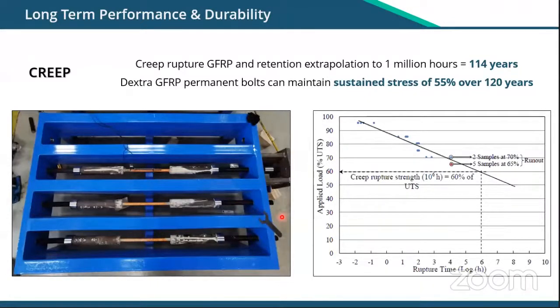First topic, creep. Again, I think it's a nickname, but I think it's a very good way to summarize it, the static fatigue. So while fatigue will have some impact on the material cycle after cycle after cycle, here creep will see the impact on the performance. So typically we are looking at retention, creep retention, and it's related to a static load. As you would expect when you do an RC structure, here we assume our reinforcement is under a constant stable load, and we want to see the effect.